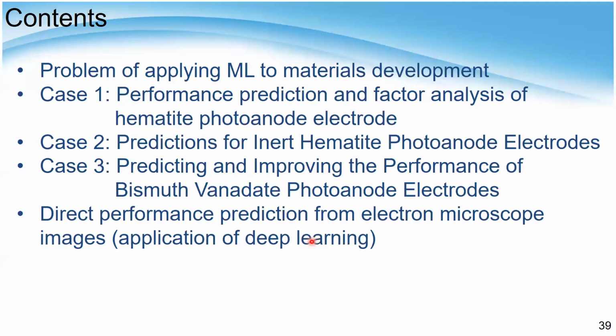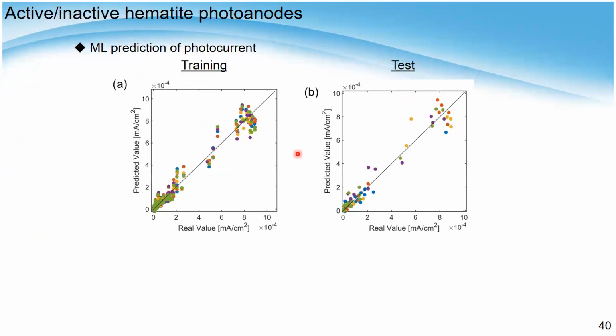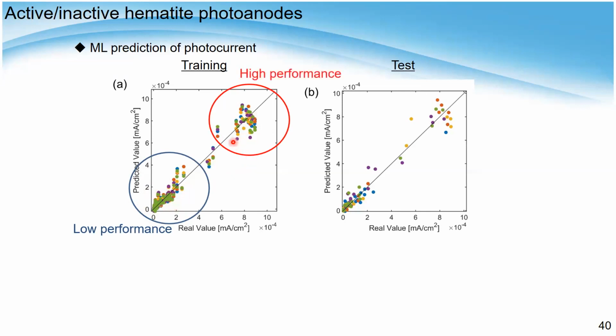So the next topic is the prediction for the inert hematite photoanode electrode. So here is the machine learning prediction of the photocurrent, as I showed, for the training and test data set, real values and predicted values. But you could notice that the data points are separated into the higher part and lower part, which indicates that this one is low photocurrent values, meaning the low performance samples, and these are the higher performance samples. But we want to prepare these high performance samples, and the same in the test data sets too.